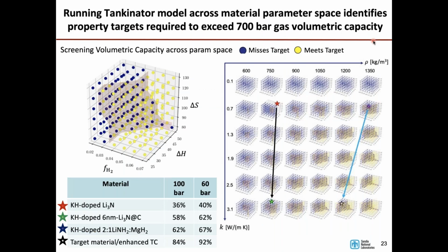Now, what I'm showing here are Tankinator calculations that we've run to get a handle on where we stand with our materials in terms of the targets that we have for the thermodynamics and the capacity and the heat transport. So what you see on that upper left-hand 3D plot there is a plot of whether or not a specific combination of properties either meets a target, and in this case, the target is to meet or exceed the volumetric capacity of 700 bar hydrogen gas. So if the little dot is yellow, it meets the target. If it's blue, it does not. And the 3D shows that for different hydrogen capacities, for the enthalpy, that's delta H, and the entropy, delta S.